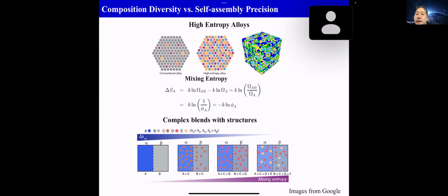And imagine if I have a diblock of polymers that's made of the A and B component, and you can imagine it forms alpha and beta phase, an A-rich and B-rich phase. You start adding a third, fourth component or even a fifth component. If you keep the solubility for the additional C, D, E components in between A and B, the C is going to disperse, and we know that. That's, you know, what a lot of compatibilizers are used for in polymer blends. And in that case, what you see is the alpha and beta phase miscibility starts to increase.